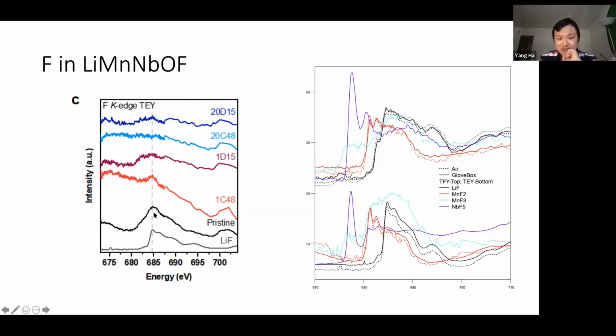And what's more interesting, we can see when we cycle, in the first cycle, we lose a lot of fluoride intensity. And in the 20th cycle, we almost lose all the fluoride signal, which suggests these fluorides were either dissolved into the electrolyte or are covered by something on top. So we can observe that using our TEY probe.